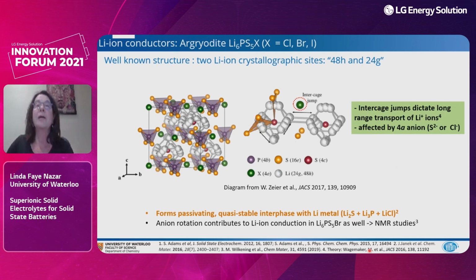So some very nice work by Marnix Wagemaker has shown that the transport in the unit cell is limited by lithium ions across these cages. So these cages sit in the 4 quadrants of the unit cell. They're called Frank-Kasper polyhedra. And the point is that the lithium ions zip around within these cages very efficiently, but they undergo a more limited intercage jump. And clearly the anion that's going to sit in this position is going to affect this jump, as will the distance between the cages, and whether or not one can introduce a little stepping stone to help that jump process occur. So I'll talk about the stepping stone first.